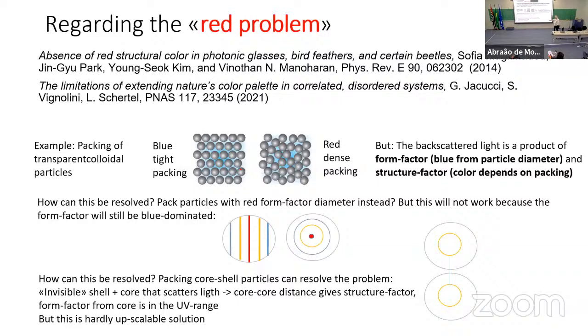So the way around this is to use core-shell particles. The distances that give interference is the distance between the cores, and you have a transparent shell around the core. If you pack those, you can get red. The problem with this is that it is not very industrially upscalable.